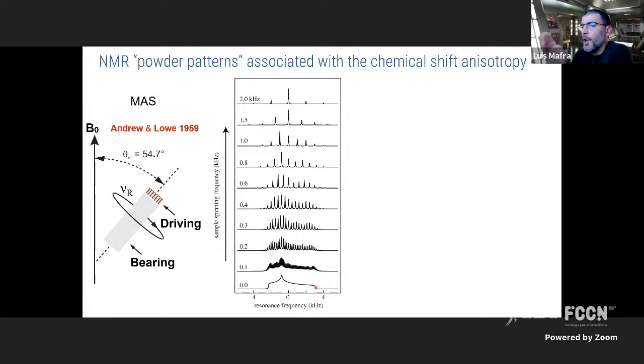So the chemical shift doesn't only depend on the chemical environment of a given nucleus, but also on the orientation of the electron cloud with respect to the magnetic field. So we call this chemical shift anisotropy. This will lead to a distribution of chemical shifts. And if you sum up all these statistics of chemical shifts, you end up with this probability curve, let's call it like that. So you can get rid of this to try to mimic the tumbling of molecules in a solution. The way you do it is magic angle spinning. And you spin as fast as you can, so you can average out this interaction.